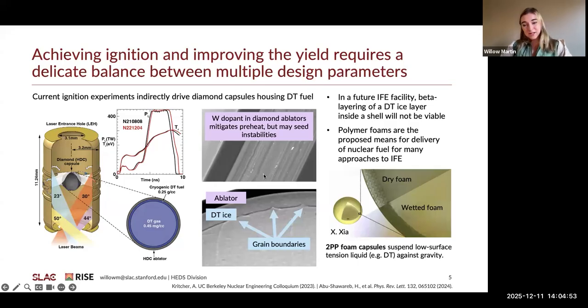For instance, hydrodynamic instabilities have to be controlled since they can mix material and inject high-Z ablator material into the hotspot, amplifying radiative losses. For example, even micron scale imperfections in these sorts of experiments can seed instabilities that grow and prevent ignition. So extreme care is taken to ensure target quality. So much so that this ice layer that you see in the center is actually fabricated as a single crystal. It's grown over many days in a process called beta layering.